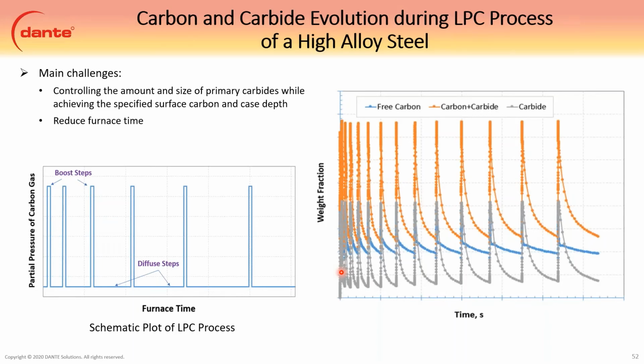So low pressure carburizing is, I boost, I give it acetylene, which is a carbon source. I give it a couple minutes, and then I suck all that acetylene out to a near vacuum, and I let the carbon diffuse, reducing the surface carbon. I then put acetylene back in, let the carbon build up, suck the acetylene out, so it's a repeating process. And as the carbides dissolve, they provide additional carbon to the matrix, right? So you have to consider them, or else you're under predicting the amount of carbon and the case depth that is actually there. So Dante has this ability.